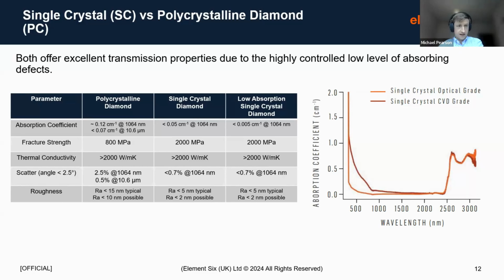But if we then have a look at our polycrystalline material up at 10.6 microns, we're expecting scatter down as low as about 0.5%. So pretty low. And the reason for that scatter, as I said, is a combination of grain boundaries. Also, birefringence in polycrystalline material is typically quite high, which leads to a lot of scatter at shorter wavelengths. And then also the surface quality that we're able to achieve.